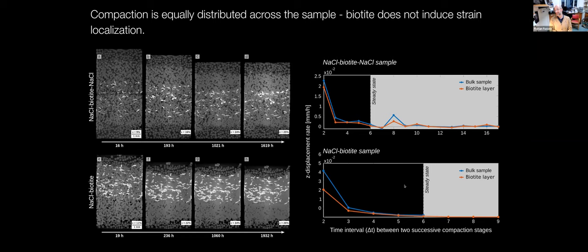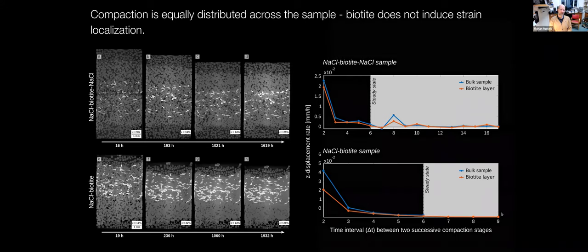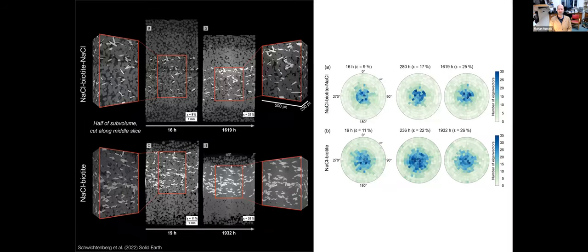That was question number one, or surprise number one, I would say, because from the sheet silicates, we did expect that to happen. It has been published that sheet silicates accelerate strain localization. It doesn't happen. And the other sample here shows the same thing. So there's a little bit of mechanical rearrangement early on, but later on, when it really counts, when we reach what we call the steady state compaction, there's no difference in the compaction. Biotite has no effect anymore.